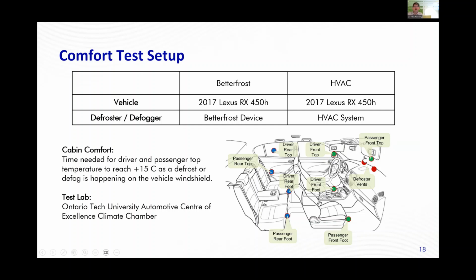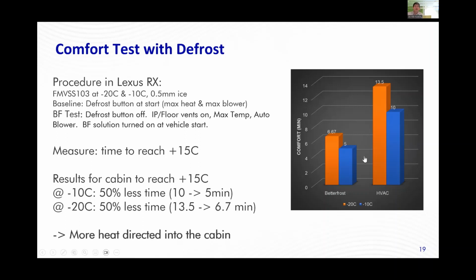We've also done comfort tests. This is how long does it take a vehicle that starts at minus 20 C or minus 10 C to get up to plus 15 C. We've done this for both defrost and defog. In this case, we're showing the defrost results and the time to reach plus 15 C. And it's about a 50% reduction in time to get from minus 10 C or minus 20 C all the way up to plus 15 C. And what's happening here is more heat is being directed into the cabin rather than diverted up to the windshield. So this is more passenger comfort, faster from a cold start.